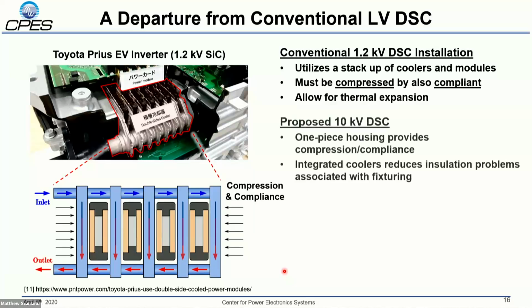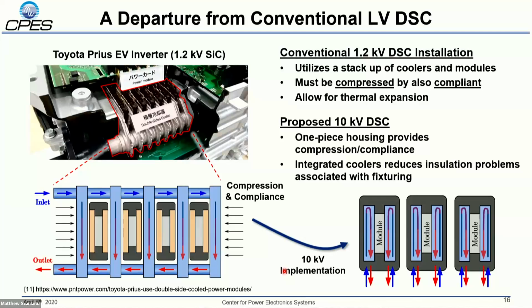So part of the strategy by integrating these coolers is also using a one-piece housing. And the idea here is that we no longer need compression to get a good thermal interface between the cooler and the module, because the cooler is now integrated into the module. But that's not the only reason for compression. There's two reasons for this compression. One is to get that thermal contact. The other one is actually to provide mechanical support to the module.